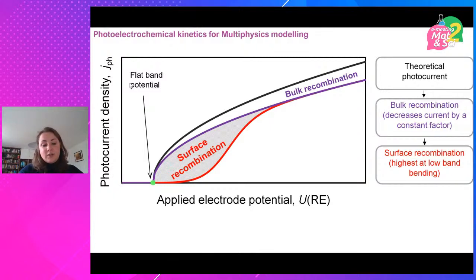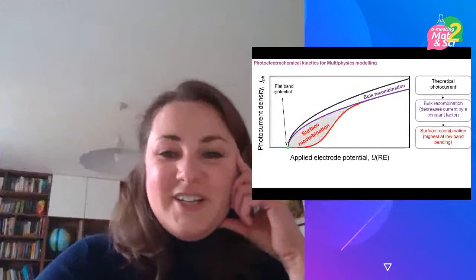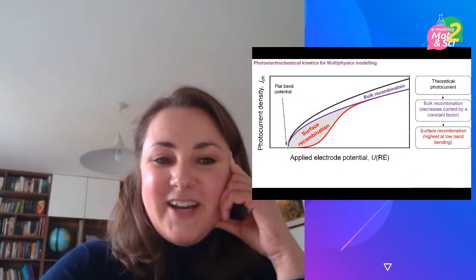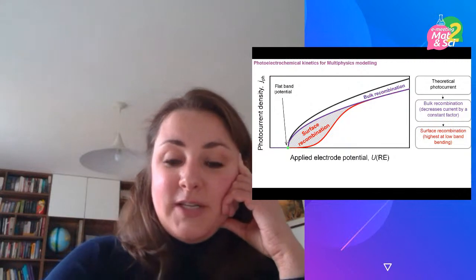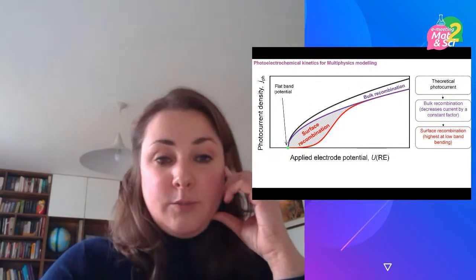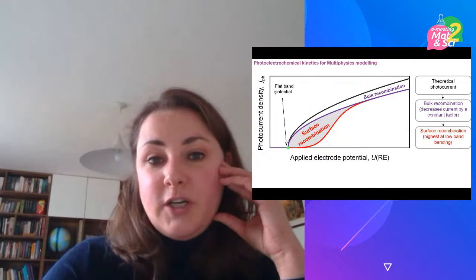So that's why so often in publications, the value of the flat band potential is quoted, because if you're able to change that and bring that, for example, to more negative values, then that's an achievement, because it means that you have earlier photocurrent onset. So incorporating this flat band potential into the model is essential. And that's where I first experienced the pitfalls of actually trying to find it. And after finding the flat band potential, you can then assess how the observed kinetics are different to the predictions.